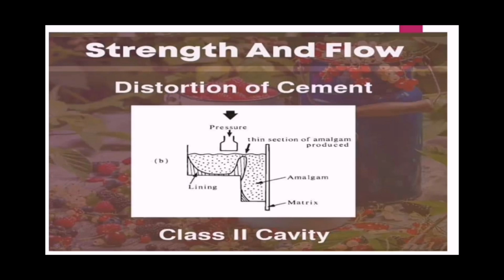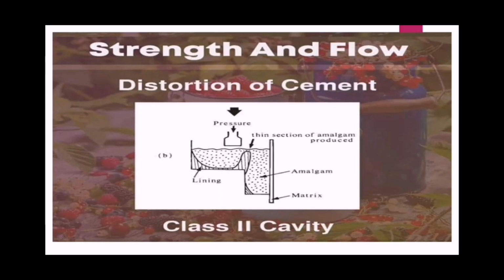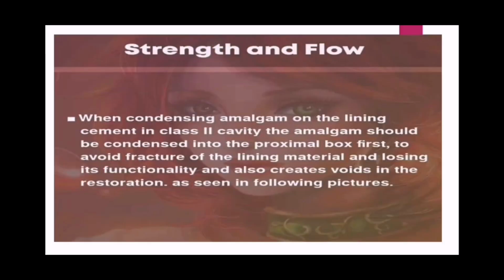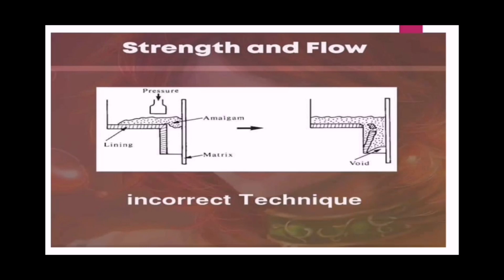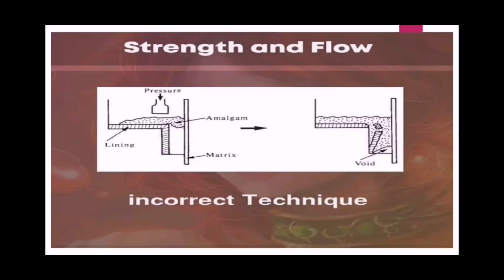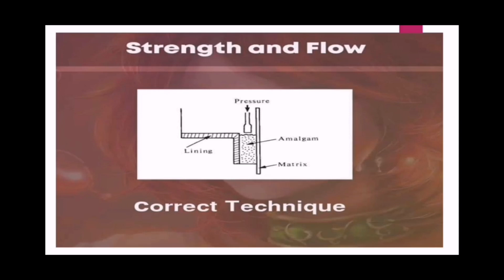When we apply a filling material by a condensation process, like amalgam, we apply condensation forces, and distortion of the cement takes place. Strength and flow. When condensing amalgam on the lining cement in a class 2 cavity, the amalgam should be condensed into the proximal box first to avoid fracture of the lining material and losing its functionality, and also to avoid creating voids in the restoration, as seen in the following pictures. This is an incorrect technique. This is the correct technique used for the class 2 cavity for amalgam condensation.